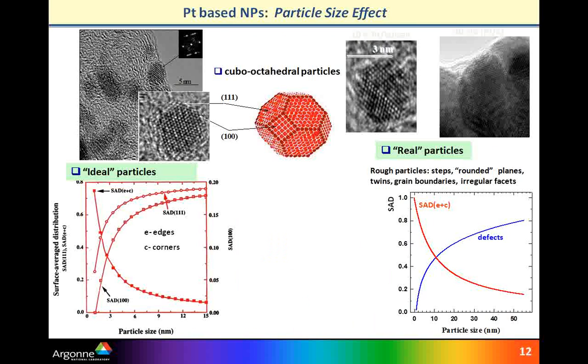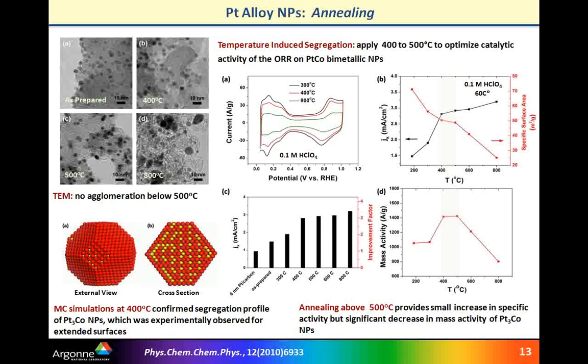So once we established the particle size effect, we proceeded towards another challenging question, and that was whether we could mimic platinum skin type of behavior at nanoscale. So on single crystal surfaces, as Nana mentioned, platinum skin was achieved by annealing. And it is also well known that if we anneal a nanoscale catalyst, then we can basically sacrifice that nice and unique particle size distribution, because a substantial amount of particles are going to agglomerate, and therefore instead of an average particle size of 5, we would end up with something like what is shown here in inset D, where substantial agglomeration took place. So we spent significant time exploring whether we can optimize the annealing temperature to the level where agglomeration is not obvious, and that's a temperature between 400 and 500 C.